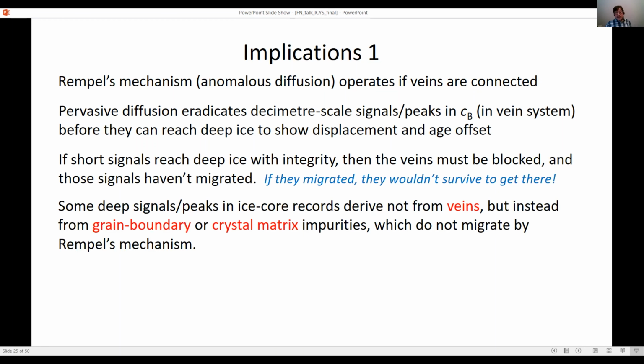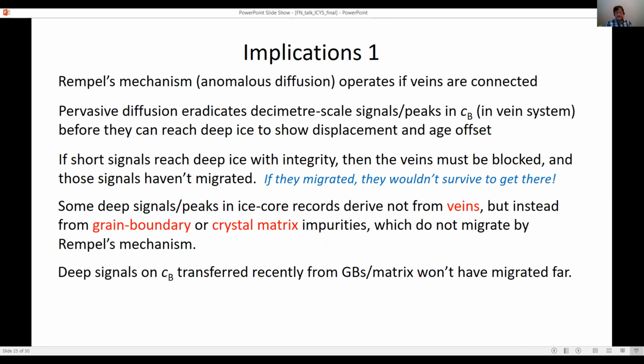Well, we've only modeled the vein signals. The actual records include contributions from grain boundaries and crystal matrices, which don't migrate by Rempel's mechanism. Some of these impurities could feed into the veins, though, and refresh the vein signals. If you see any vein signals that are short and well-defined, obtained from such sources, they wouldn't have migrated either. If they survive the diffusion, they wouldn't have migrated. If they migrate, they would wane away very quickly.